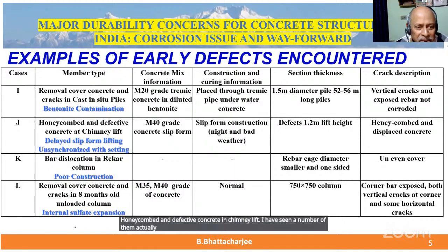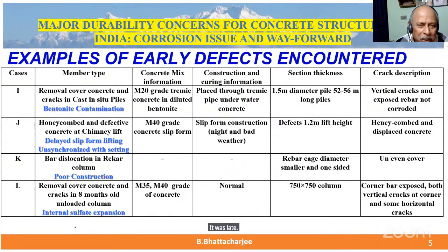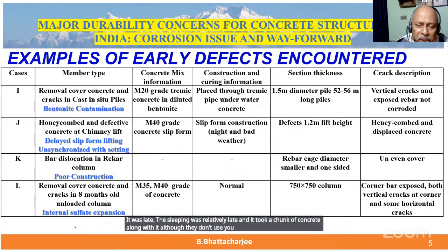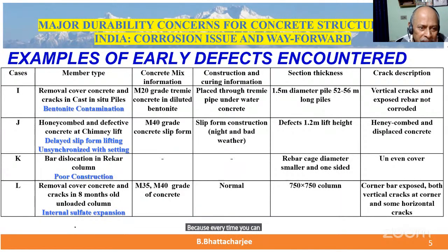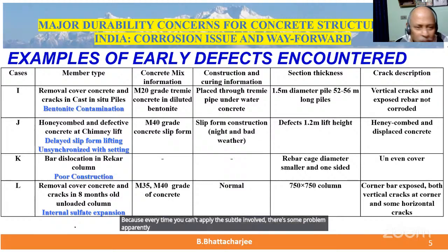Slip form construction. If they have not synchronized with the setting, the slipping was relatively late and it took a chunk of concrete along with it. Although you can't use a shuttering oil there, they use a kind of polished former, because every time you can't apply the shuttering oil, there's some problem apparently. At least in those places they were not doing it, and the concrete came out with it. So I have a photograph of this also.